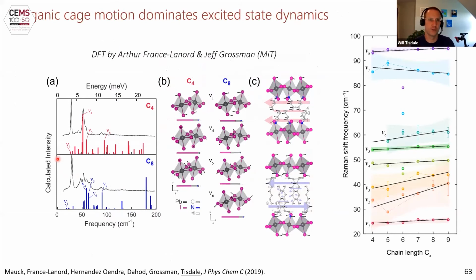And what we find overall is that the inorganic cage is really dominating most of the dynamics in these materials, that the electronic excited states are determined almost entirely by the vibrational motion of the lead halide octahedra and not by the organic cations. The organic cations' motion is involved in these motions, but it's really as a spectator ion, that these heavy iodide atoms are pulling along these very light hydrocarbon chains along with them as they vibrate.